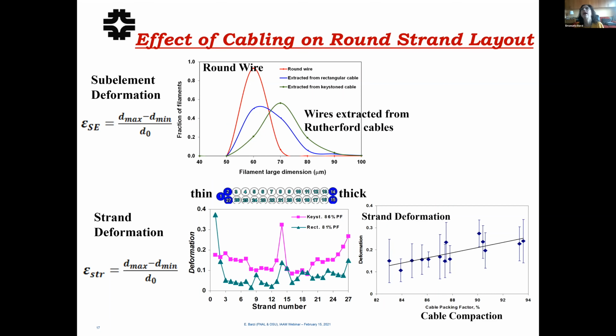So among the studies that we had to do was to check what happened to wires when extracted from the Rutherford cables and before being heat treated. So we still were dealing with a composite, but with a composite under plastic strain. So this is a complex system. And of course, we did finite element modeling to try and simulate the deformations and the behavior of this composite that was not superconducting yet. So these are examples, okay?